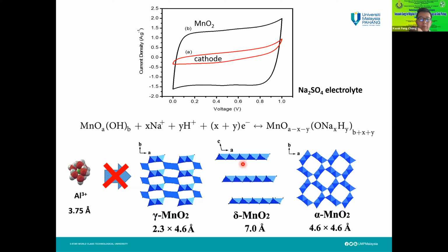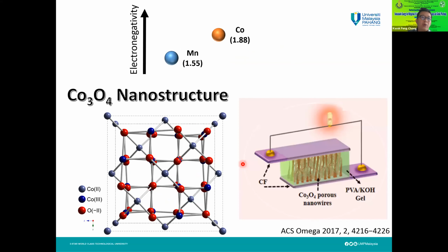So that means we failed in terms of putting the aluminum ion in. So that's why we do not consider manganese oxide anymore, because we cannot insert our aluminum ion inside. Instead, we try to find a different way. And then my group proposed, why don't we try other things, like studying electronegativity. The cobalt possesses higher electronegativity as compared to manganese. We hope that by increasing the electronegativity, we can pull this aluminum ion so that it can stay longer and go into the void of this crystal structure.